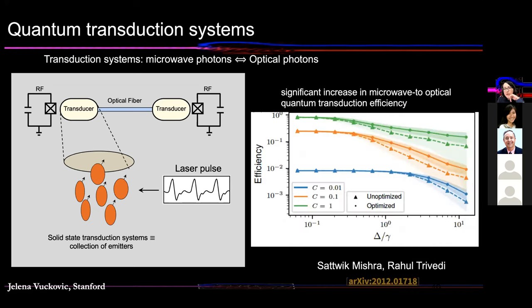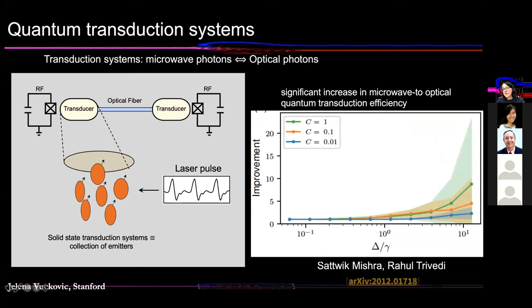We have shown that just by applying the optimized optical drive or microwave drive on the whole ensemble, we can reduce inhomogeneities. And this is an optimized drive that we find by applying these quantum inverse design optimization techniques, by knowing this inhomogeneous broadening in the ensemble. As a result of that, we can increase the efficiency by a factor of 20 already. And that's for an ensemble of 10 atoms and very modest parameters.